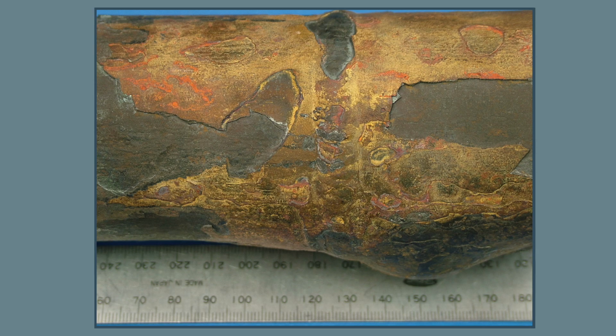Actually, you make a good point there, Vanessa, because with these high temperature ruptures or failures, the spheroidization actually changes. So the lamina is what gives steel its strength. And because it's spheroidizing, you're losing strength in your steel. And that's what in the end causes the rupture. Your section thickness is designed to handle a certain pressure. And when the material starts spheroidizing, it becomes softer. So then it fish-mouths, it bubbles, like you see in the image, due to hotspots or higher temperatures. And that's because the scale forms like a blanket, so it just gets warmer and warmer on the tube surface. And that's when it has that plastic deformation. And then the material that has spheroidized or softened ruptures because it cannot hold the strength that the boiler tubes were designed for. So that's when the rupture occurs.